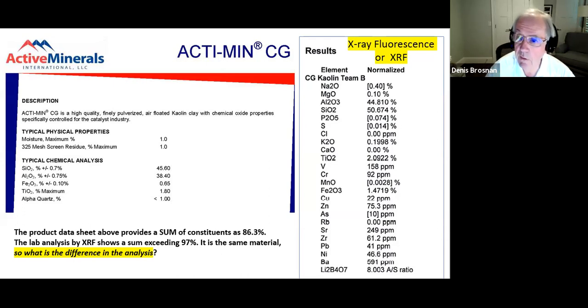Well, on the right, you see an X-ray fluorescence, XRF analysis of the same kaolin from one of the classes that I taught. You see alumina, 44.81%. Well, that's about 45%. You see silica, 50.67%. In that case, it's a bit higher than the silica on the data sheet. And you see a lot of other constituents there that are present in the full chemical analysis.